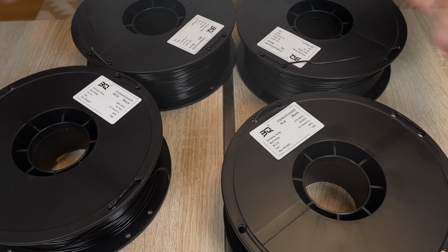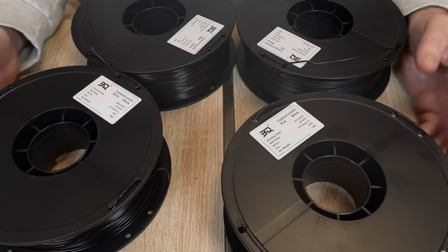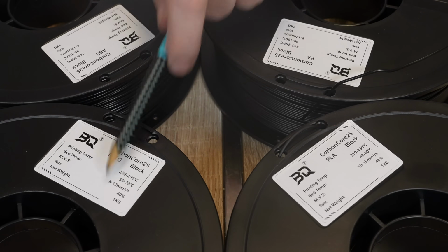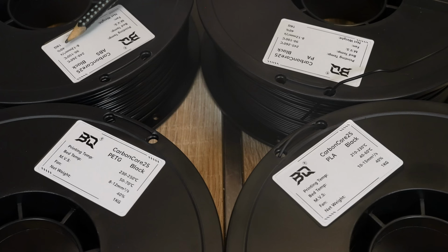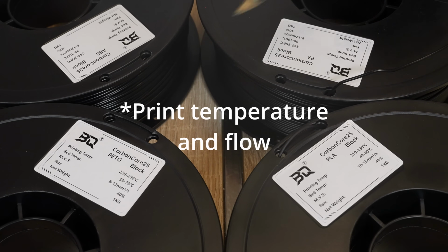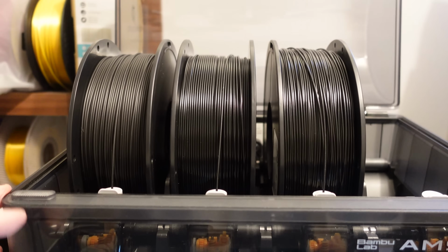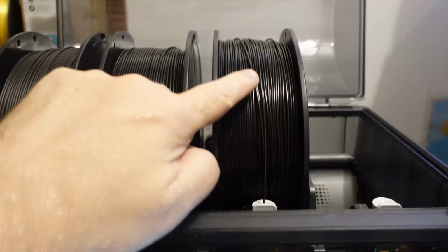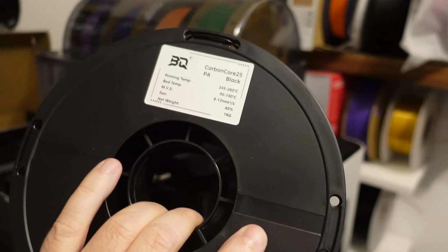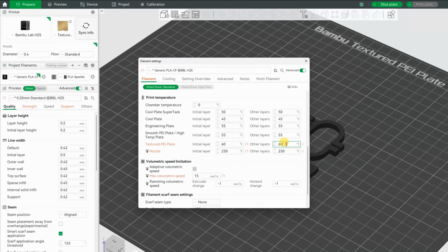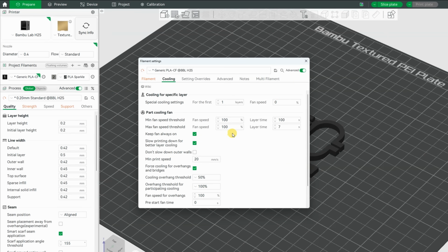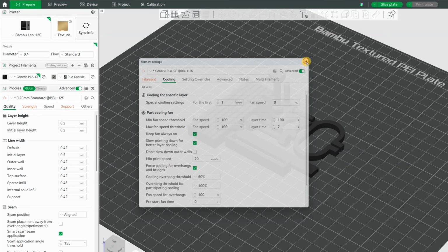And I can confirm that basically each of these filaments can go into the AMS. And now I noticed some additional information about the part cooling fan, which is 40% in each case, which is a little bit weird. I think I will use the generic profiles for these base materials. Only the print settings and the maximal flow will be according to these numbers. Three filaments are loaded into the AMS: PLA, PETG and ABS. Only the polyamide or nylon will be dried before the printing. Print settings for the PLA: 60 on the bed, 230 on the nozzle, 15 the maximal flow and the maximal part cooling. And of course my typical test objects.